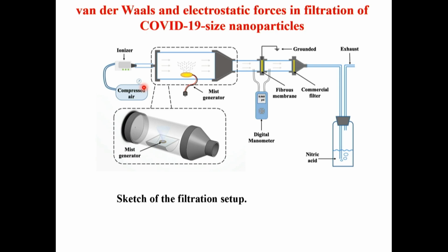We try to catch them using van der Waals forces, number one, and also adding electrical forces, number two. How do we add electrical forces to metallize nanofibers? We developed a process, and I'll tell you about it later. Electroplating makes fibers thicker, and we don't want them to become too thick. So we take our 50 nanometer nanofibers and sputter coat on them. Then we have van der Waals active nanofibers with metal coating altogether below 100 nanometers. So we can make the filter essentially a part of an electrode and catch particles by means of van der Waals and electrical forces.